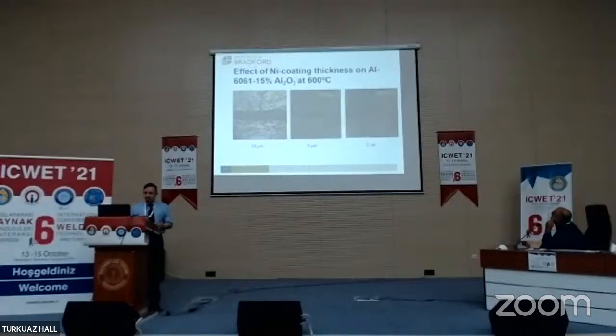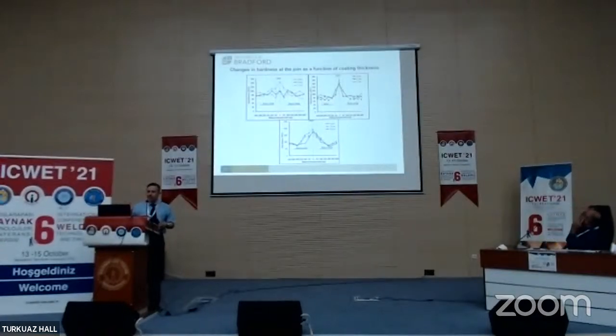And what we find is that with these particles, if you have a thicker coating, 15 microns, we have the segregation effect. But if we control with the thickness of the interlayer, then the particle dispersion is less destructive within the joint region. So we can combine both the combination of nanoparticles to strengthen the joint and also control the thickness of the interlayer that we are using. And this is what you see here. So in the beginnings, you see a very high peak in the middle for all of them. Here, we see a peak, but it begins to decrease, and the width increases as well. So there is more uniformity as we reduce the thickness, but also have presence of particles. So the alumina particles will give the higher hardness in the joint region.